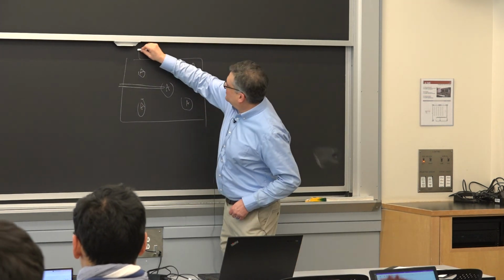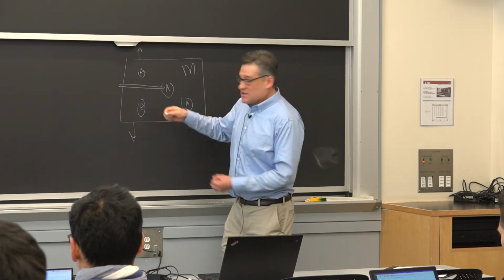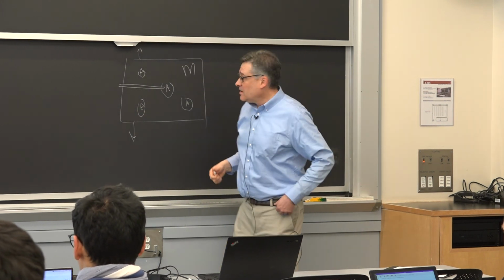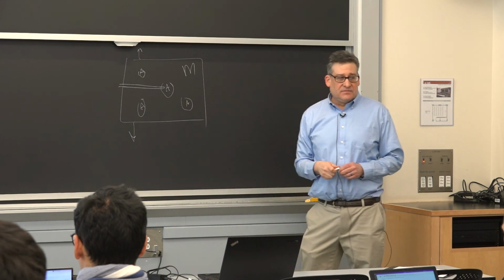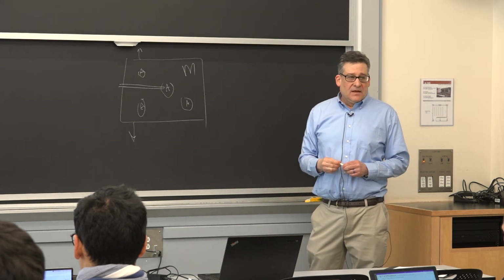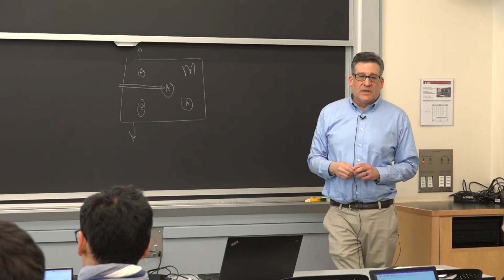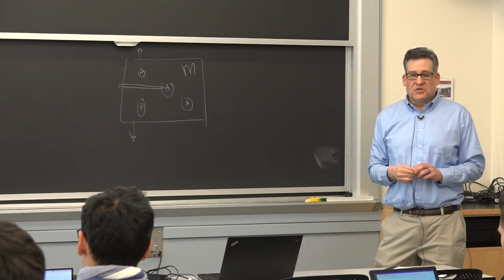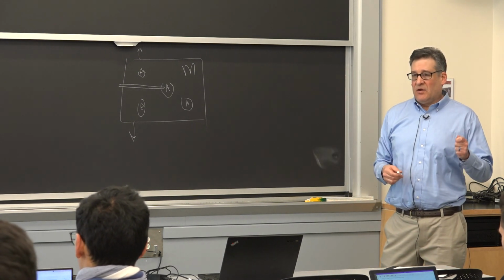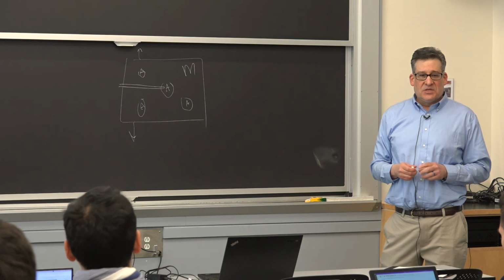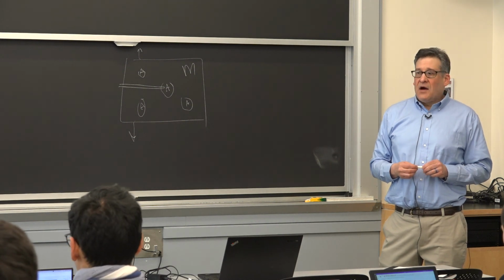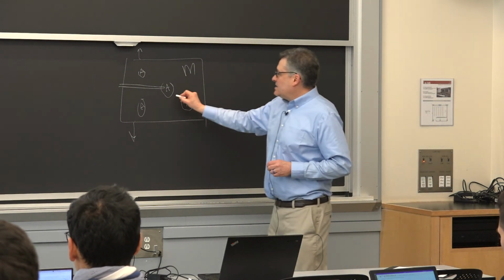Suppose it's being loaded like this, so you're stretching open this piece of material. As this crack propagates through this martensite, because the martensite is so brittle, because there's so little possibility for dislocation motion, because the grains are so small and it's so good at tying up dislocations, the material can be kind of brittle.